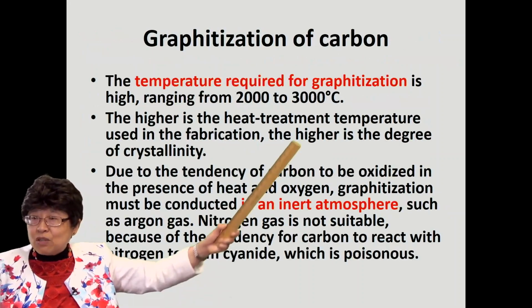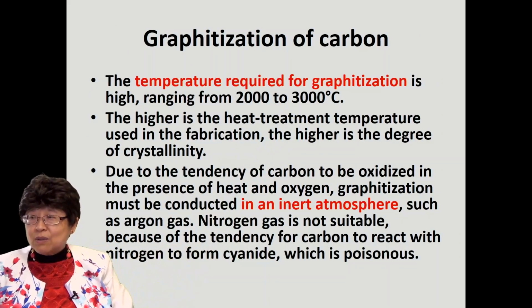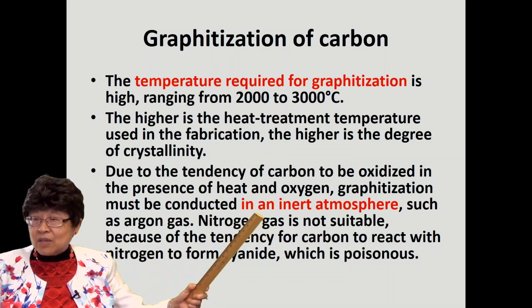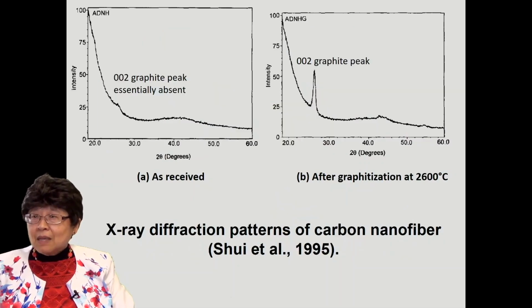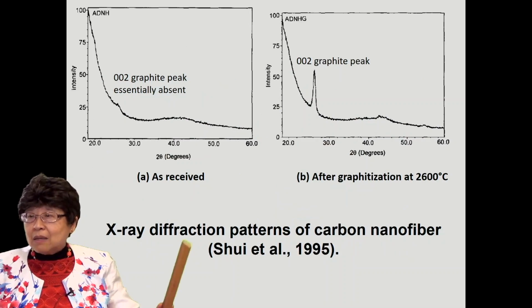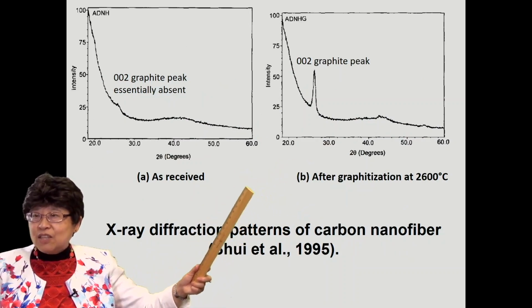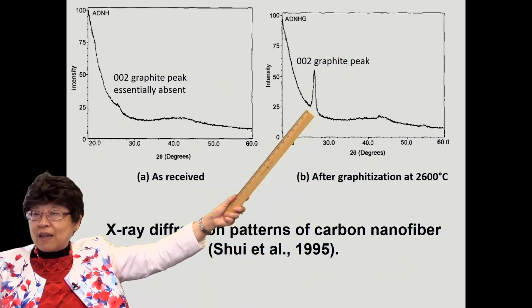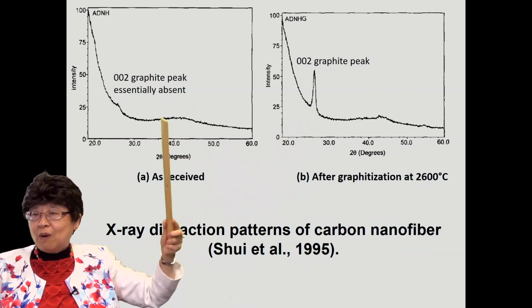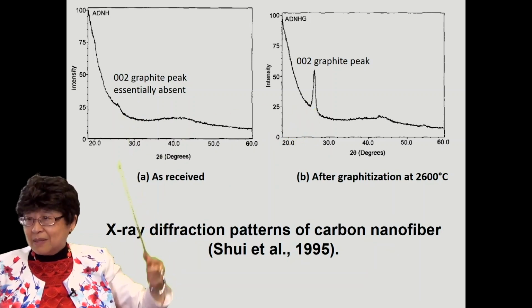It needs high temperatures like 2,000 to 3,000 C, and it needs an inert atmosphere. And upon such graphitization, the X-ray diffraction peak shows up. Before, it essentially doesn't show up. Okay.